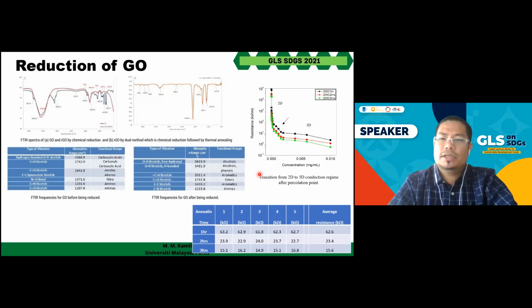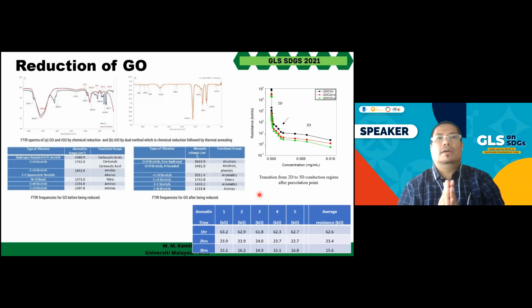And then we measure the resistance in the range of a kilo ohm across different concentration levels. Based on our thin film, because most of our applications are on graphene thin film on a silicon substrate, that's the reason why we have to have basic information in terms of the electrical conductivity, the resistances, based on the thin film on top of our silicon substrate.